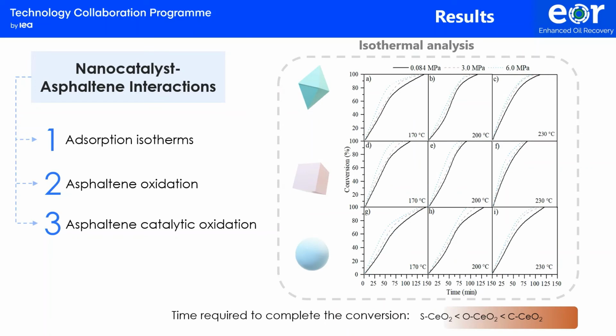As for the catalytic isothermal analysis, it was obtained that the time required to complete the conversion increases in the order spherical, octahedral, and cubic. The system that required the longest time was the cubic nanoparticles, which at 0.084 megapascals and 170 degrees Celsius took 150 minutes to convert 100% of the absorbed sample.